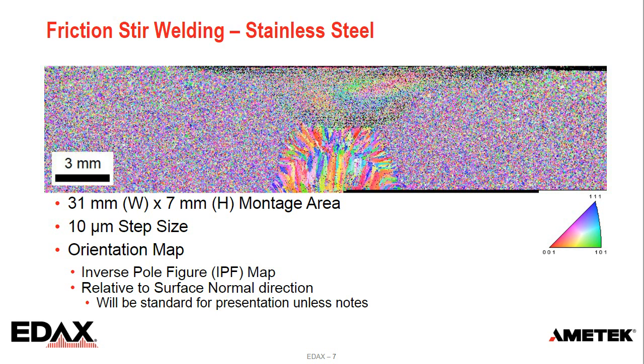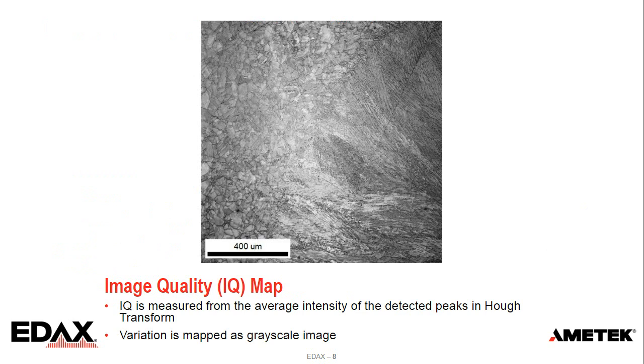And we have the little colored stereographic triangle that shows how the colors correspond to orientation. So if it's red, it's a 001 cube face orientation for the cubic faces in steel. If it's blue, it's a 111. And so we can see the weld nugget there in the bottom center. You see a little bit on the top where it's transitioned, and you see the base metal to both sides. If we zoom up along the interface in there, this shows what we call our image quality map. Image quality is a measure we get from measuring the average intensity of the detected diffraction peaks in the Hough transform. We measure that value, and then we map the variation as a grayscale image, and we see different contrasts.